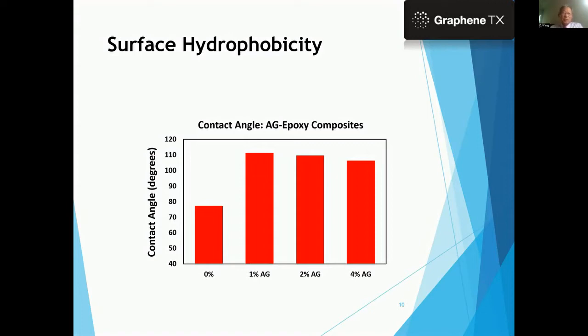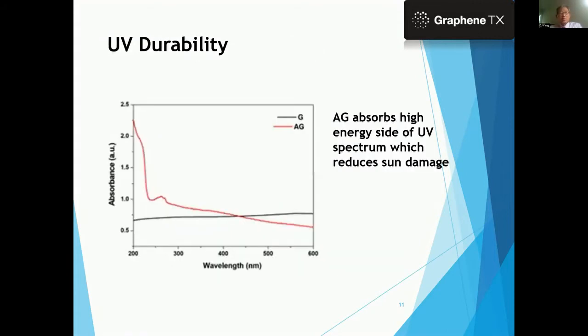Okay, then, theoretically, 1 gram of graphene can cover 2,630 square meters. So if you put it in the composite, there are multiple layers of graphene, and so they will protect against the moisture problem. And then another advantage, as you can see, just using pristine graphene, it doesn't absorb UV light. However, aminated graphene can absorb the high energy side of UV. So it will give you longer stability of a composite by using the aminated graphene.